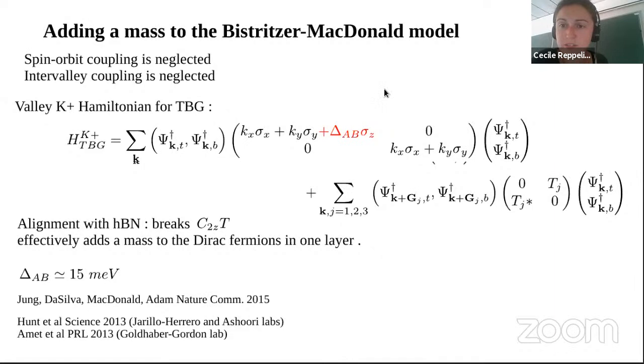This is a little bit subtle because in principle, since the two lattice constants, the one of HBN and the one of graphene, are not exactly the same, you should basically add a plus delta AB sigma Z on one zone of the superlattice, and then half a period further, you should have a minus delta AB sigma Z. But it turns out that effectively, this is not what happens. It's enough to just add this one uniform term on the whole lattice.